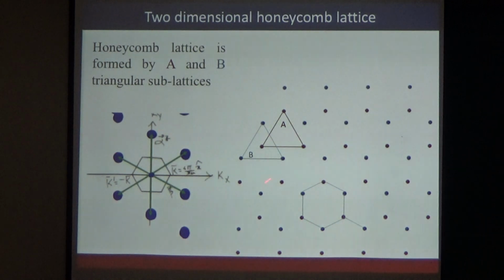These honeycomb structures have, in reciprocal space, a Brillouin zone that you can draw, which is also hexagonal, and it has two particular points that are very interesting points in the Brillouin zone, and we know these values are around 4 pi by 3a, and this is minus k. And then people did pen and paper calculations a long time ago, around 1947, of the electronic band structure of these honeycomb lattices.